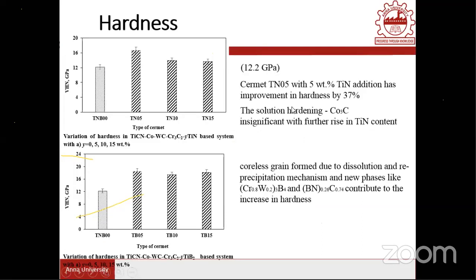Now, if you look at the hardness value, with increase in TiN addition, what is the effect? Now TNB00 is taken as the material for comparison, because no other secondary carbides are added here, which has TiCN and cobalt and also Cr3C2 and tungsten carbide, and the titanium nitride or titanium diboride is not added there. So the cermet T is TN05.